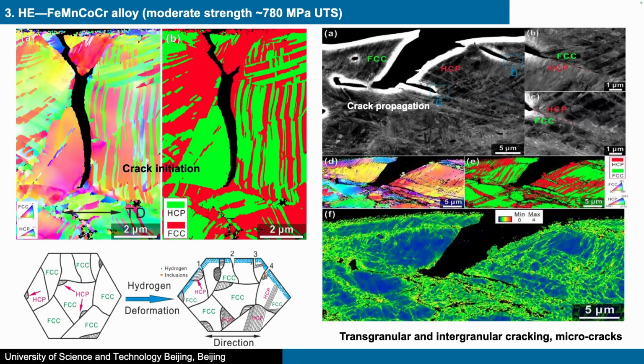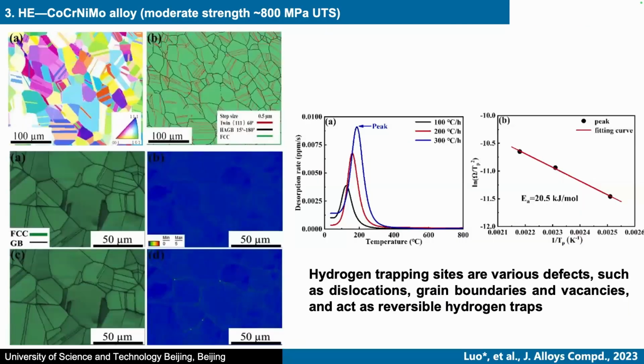And also we found the crack initiation in the FCC phases. And also we observed the transgranular and the intergranular cracking, and also some microcracks are formed in the microstructure after deformation. Here we choose another type of high entropy alloys.